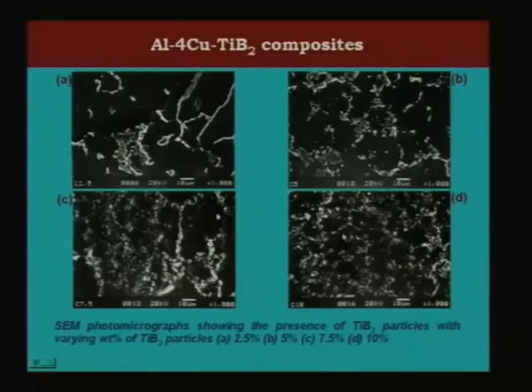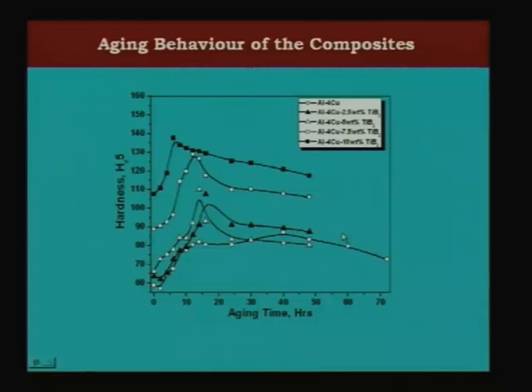The magnification is very low, so that is why you can see very fine particles of TiB2 which are uniformly distributed in the matrix. And if you look at the age hardening phenomena of this particular alloy, you can take the base alloy, for example, which is nothing but this bottom curve with the open circles that you can see here. That shows you that the strengthening that you can achieve is lower than what you can achieve with all these particles. So when you add different volume fractions or different weight fractions of TiB2, you can have much better strengthening because of the presence of TiB2 particles.